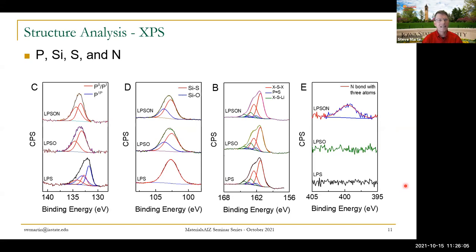We don't have any NMR techniques to identify nitrogen yet. So mostly focus your attention on the far right frame where we look at nitrogen, but we can identify the phosphorus structures, the silicon structures, and we can also identify the sulfur structures. But what's interesting is, perhaps as expected, we can identify the nitrogen through XPS. Of course, the pure oxysulfide has no nitrogen, and the pure silicon sulfide, phosphorus sulfide glass has no nitrogen. We can deconvolute this one and identify that the nitrogen goes into the glass as a tri-coordinated nitrogen. That's a lot to have for a seminar today, but there are two types of nitrogens possible. One is a doubly bonded nitrogen, and one is what we call this tricluster.